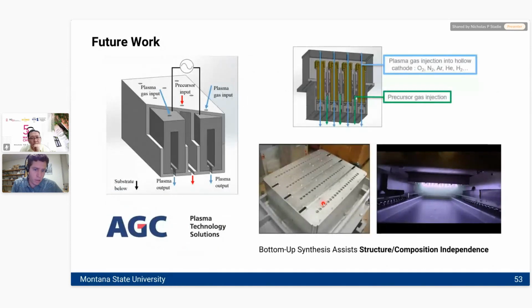Other things we're working on in our group are different ways of synthesizing silicon, and here you see a new plasma enhanced coater that we've recently started to commission. And so, yeah, making silicon in a roll-to-roll process directly from a plasma, where you just take silane and you deposit silane directly onto copper foil.